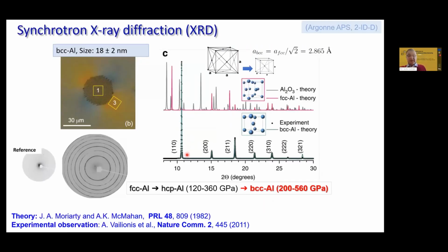To characterize what is in that modified volume, you simply need more material. We inscribed larger volumes of modified sapphire, and experiments were carried out at Argonne. The X-ray diffraction pattern has a very symmetric structure, which was surprising because we were expecting something out of compressed sapphire, which would be those magenta peaks shown here, and nothing similar was observed in the experiment. It was a very symmetric pattern, a hint that we have a very simple structure. It turns out that we have body-centered cubic aluminum. It was predicted that it can exist at very high pressures, and it was demonstrated experimentally in this way, by modifying sapphire rather than starting with aluminum.